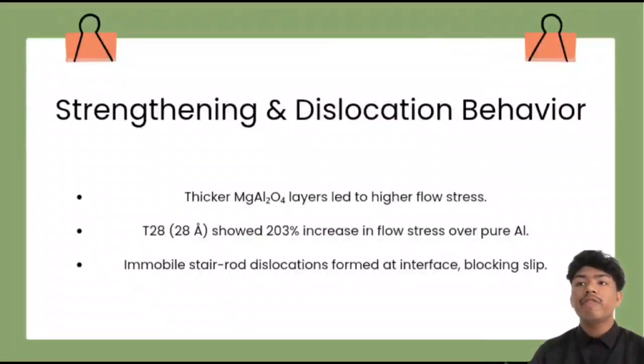Next, the mechanical strengthening effects were evaluated through tensile tests in MD simulations. The results show that adding a magnesium aluminate layer significantly increased the material's flow stress among all models, with T28, the 28 angstrom thick ceramic layer, producing the highest flow stress, showing a 203% increase compared to pure aluminum. The atomic scale mechanism behind this strengthening was explored using dislocation analysis. Simulation revealed that a stair-rod dislocation formed at the interface. This dislocation is immobile and acts as a strong barrier, blocking further dislocation movement across the interface. This is what causes the observed strengthening. Thus, the combination of thickness and dislocation blocking effects explains the improvement in mechanical performance.